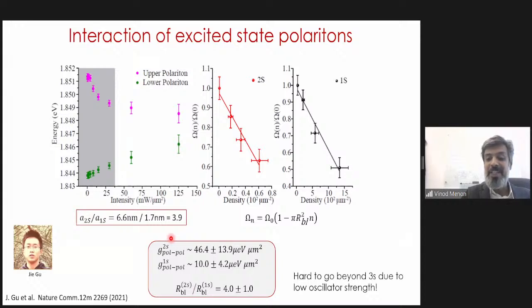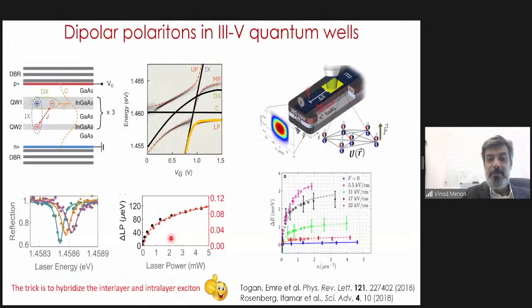But the problem is that it's not easy to go beyond 3s. And so, we were struggling with how to do this. And this brought us to another idea, and that is that excitons by themselves don't have a permanent dipole because they're all in the plane usually in these quantum well systems. But there is another kind of exciton which can be formed where the electron and the hole sit in different layers. And if you can hybridize the two, then this essentially results in an effective interaction with a permanent dipole moment, so your Coulomb interaction is much larger.